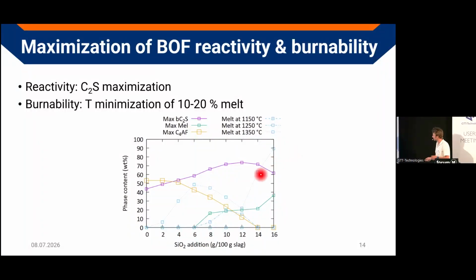And yeah, maybe something else. We also track the amount of melt which is formed at a certain temperature, because first, practically it's very nice if you don't melt down your material if you are working with platinum crucibles. But also, in industry, you would target some 20-25 weight% of melt in your kiln, and if it happens in a wide temperature range, that's also quite nice. So you see here, for instance, the 20-25 weight% has quite a big temperature window. Here, there's 100 degrees between these points, and so that's quite well manageable in a kiln.